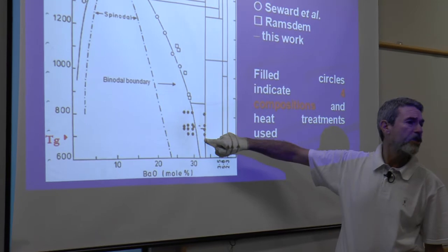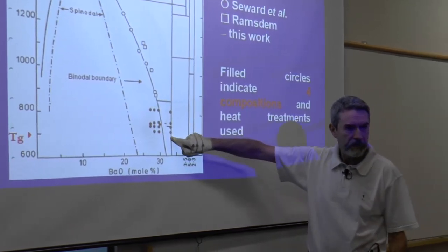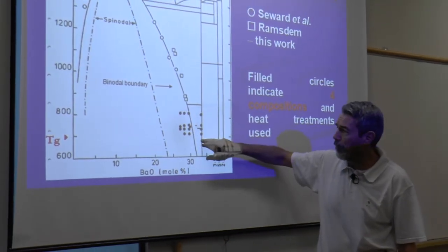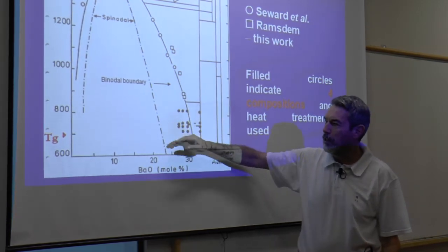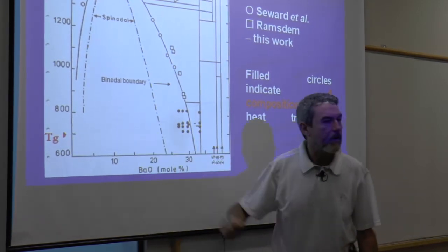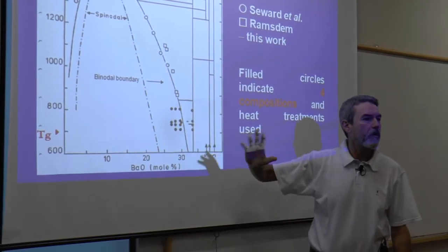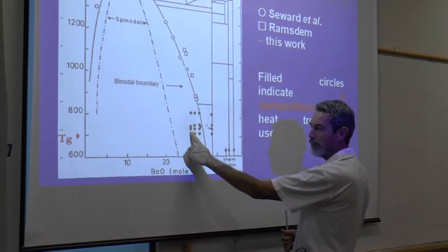This is the Tg, where the viscosity is 10 to the power 12 pascal second. So we are working a little bit above Tg. Of course, Tg increases somewhat with the silica content. Well, we are just at or above Tg. So let's take one composition, this composition here.